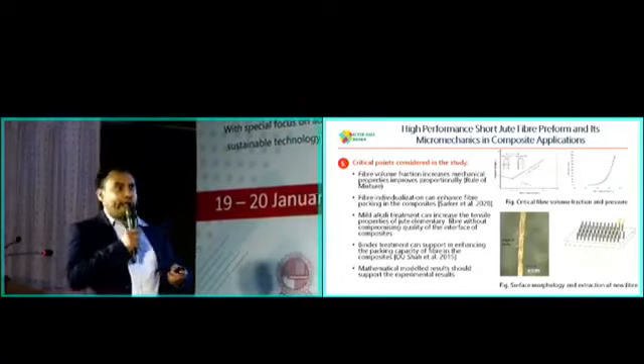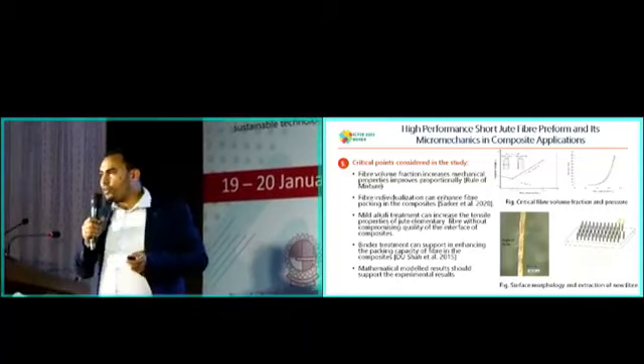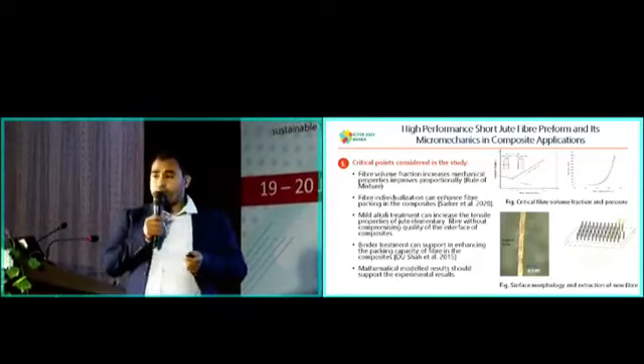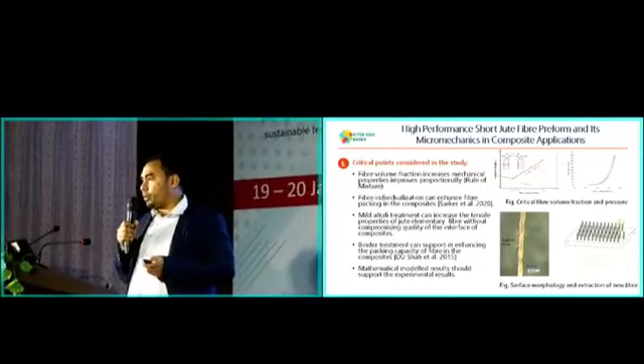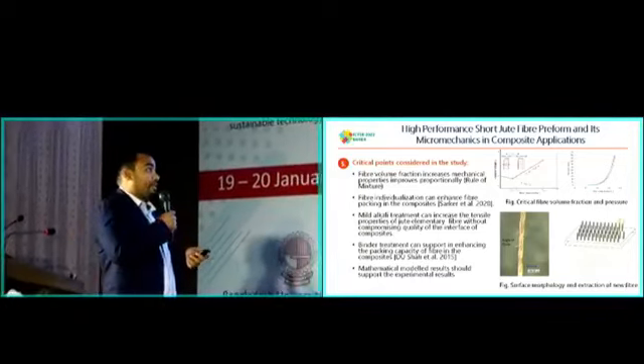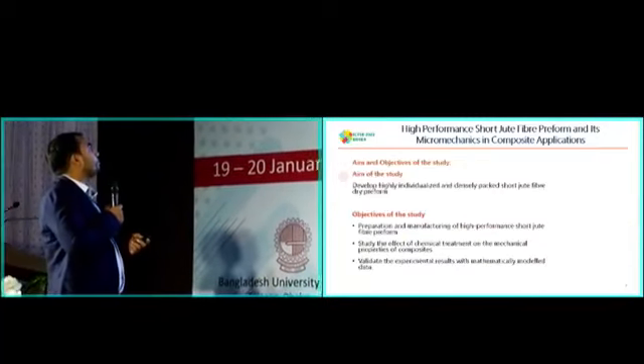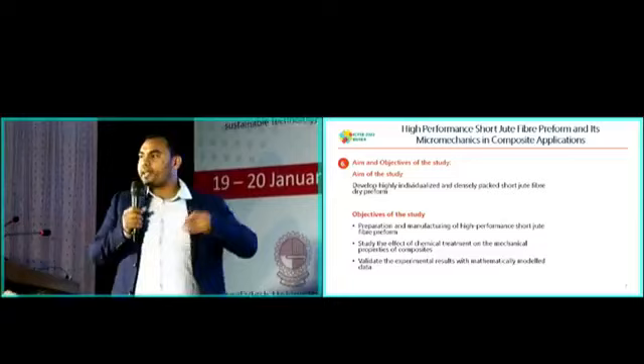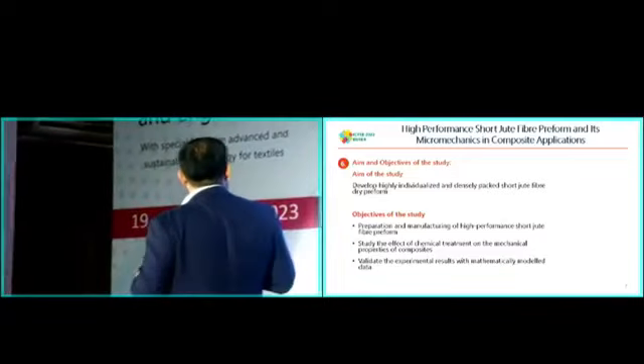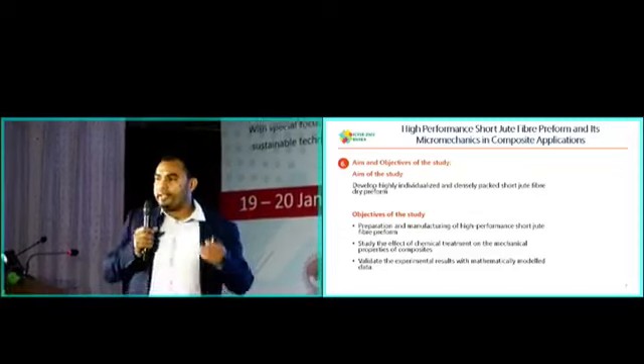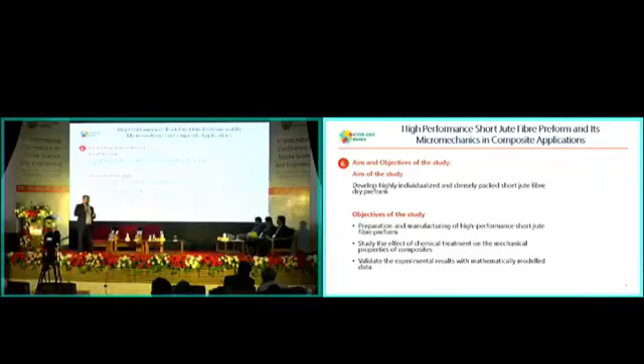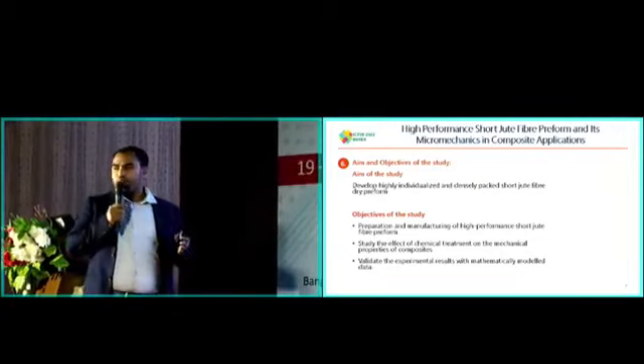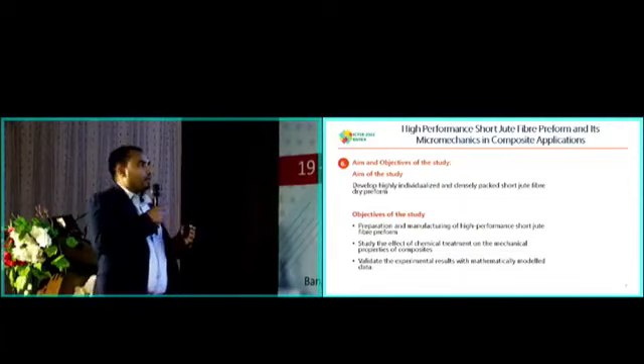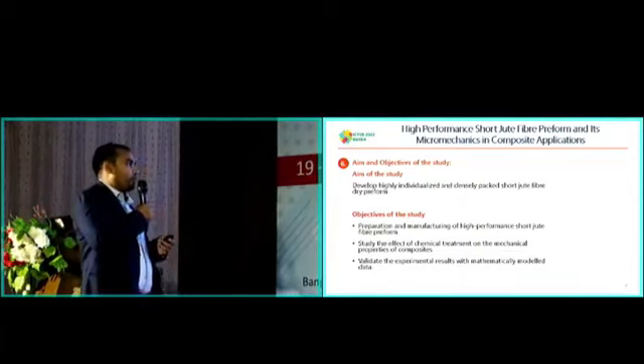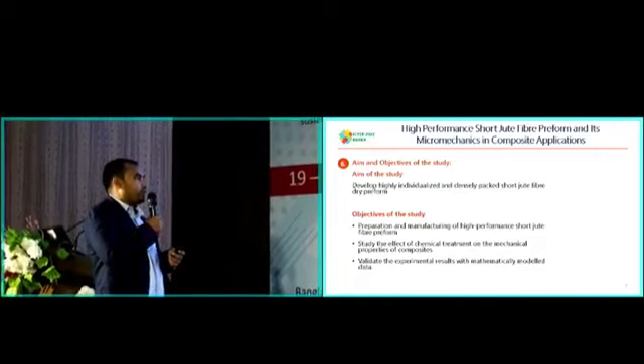So we adopted three approaches: increasing the pressure, fiber separation, and overall modification of the fiber by chemical treatment, in order to achieve the maximum fiber volume content in the composites. Therefore, by considering all the critical points, we decided to develop a highly individualized and densely packed short jute fiber preform for composite application. We set the objective to prepare and manufacture by adopting different techniques so that we can produce a preform suitable for high performance application, and also study the effect of chemical treatment on the mechanical properties of the composites.